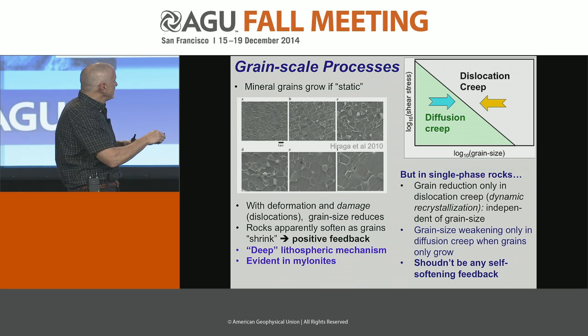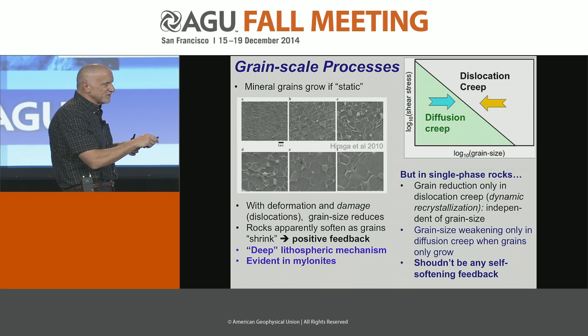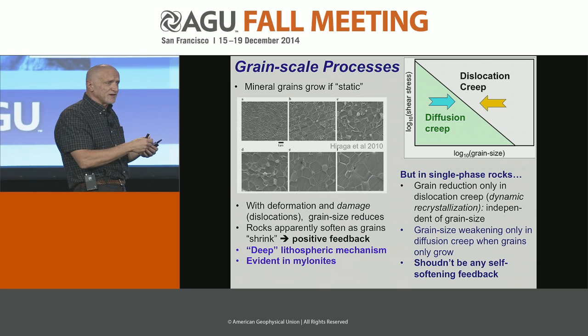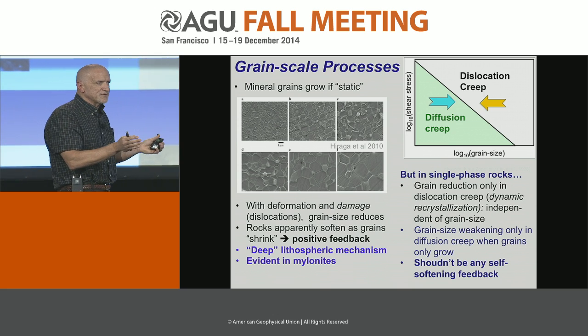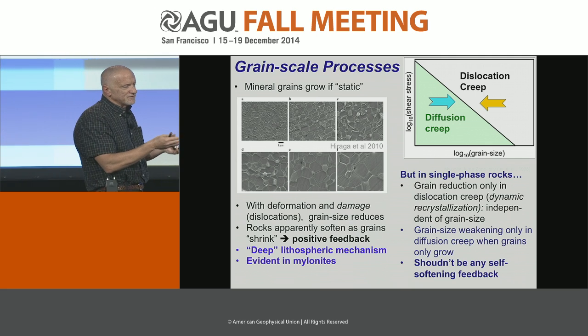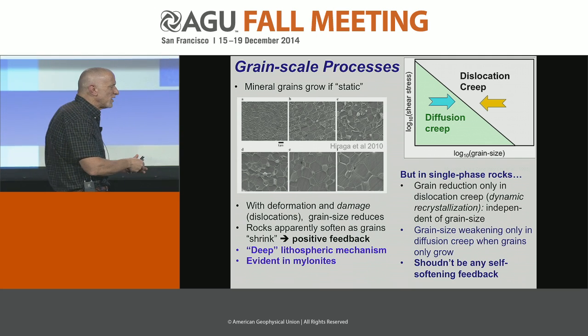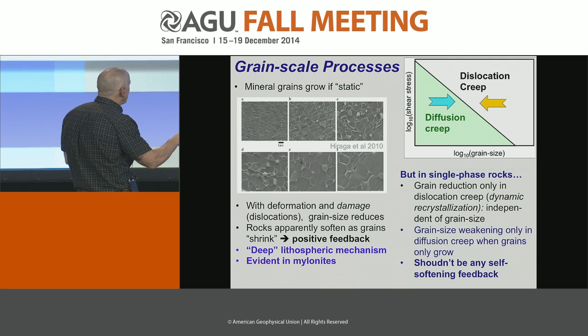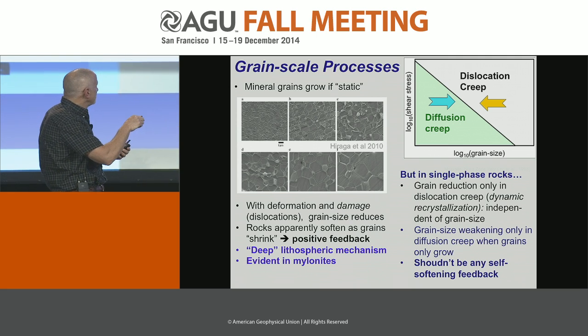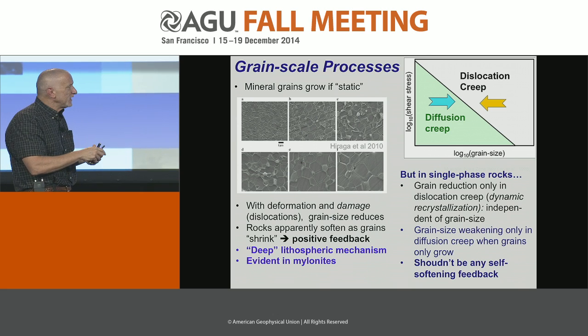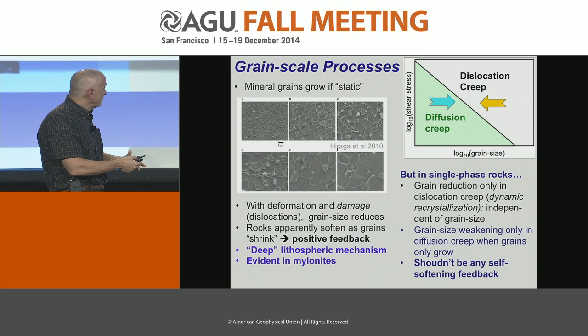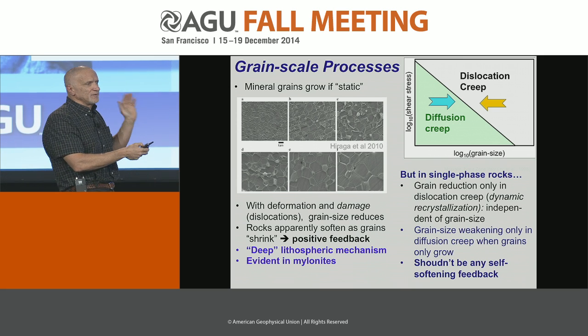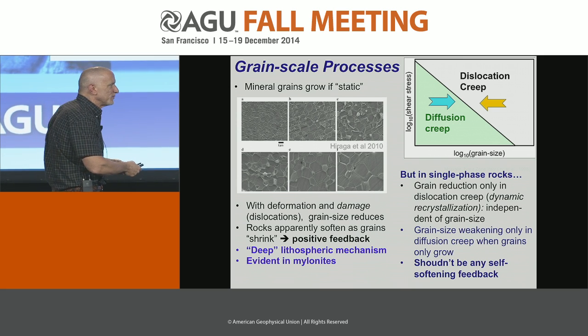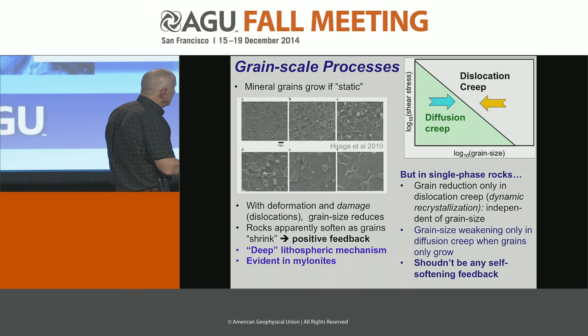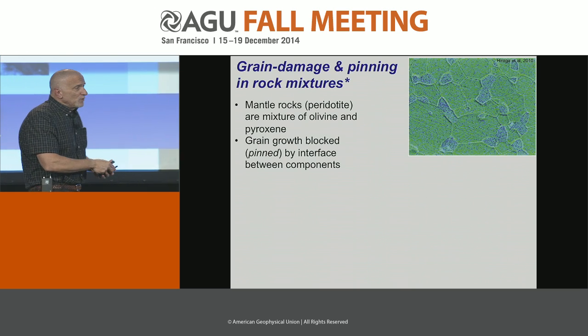Likewise, if you get into diffusion creep in small grains, it may become softer, but the grains won't shrink. They'll only grow because there are no dislocations. This has often been the quandary of this problem, that the grains will all wind up migrating to this saddle, or this line between dislocation and diffusion creep. So there shouldn't be, in principle, any feedback mechanism that we would see generating something like these mylonites.